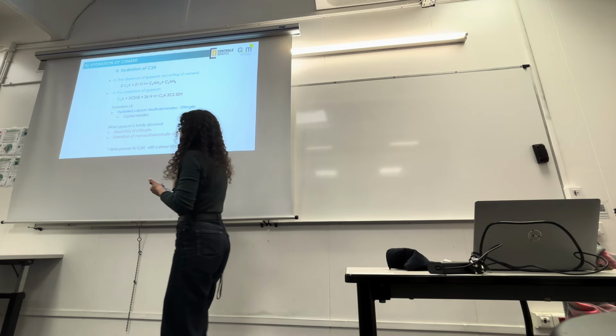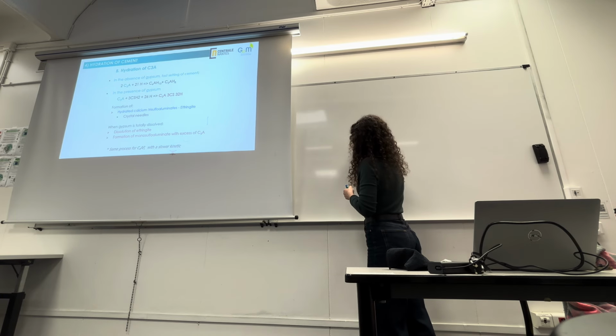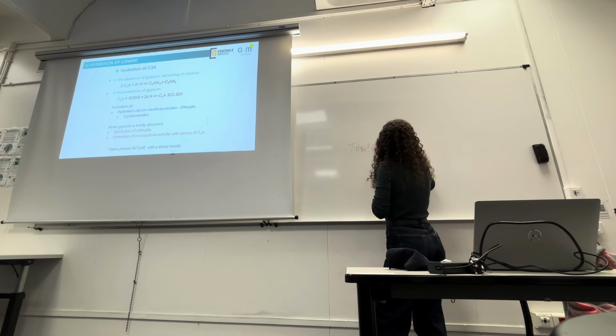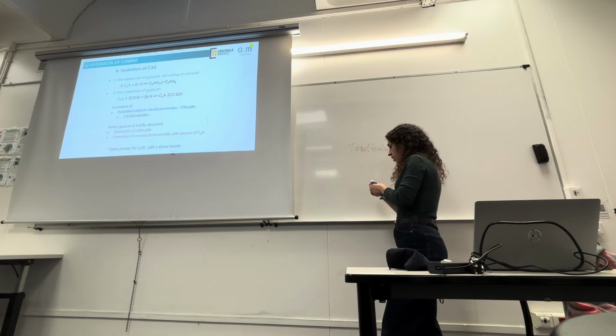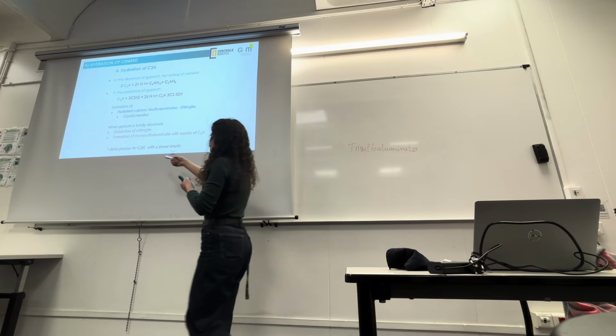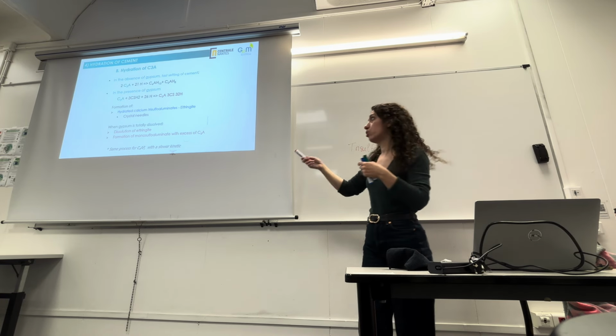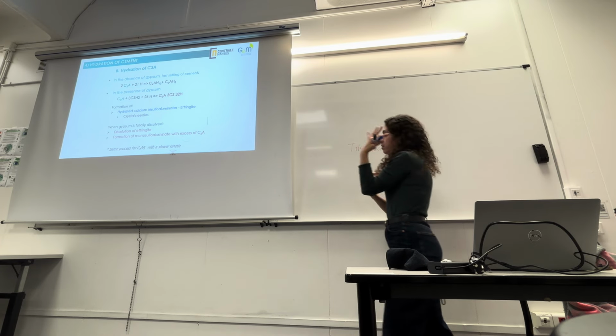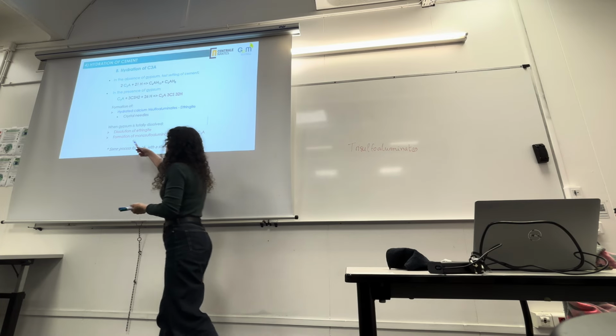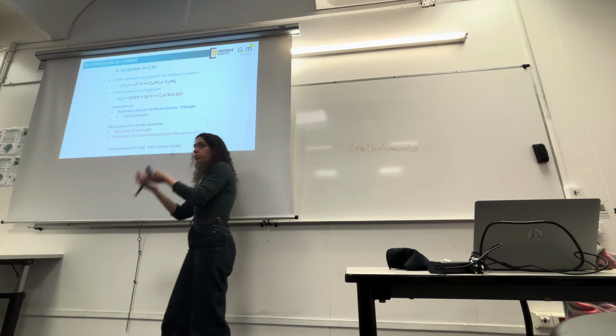So ettringite, it is hydrated calcium trisulfoaluminate. It forms by the reaction of C3A with gypsum. But then, when gypsum is totally dissolved, when gypsum is totally consumed to form ettringite, the sulfate concentration in solution is not high enough to maintain ettringite. So ettringite is dissolved and it precipitates again as monosulfoaluminate with an excess of C3A.